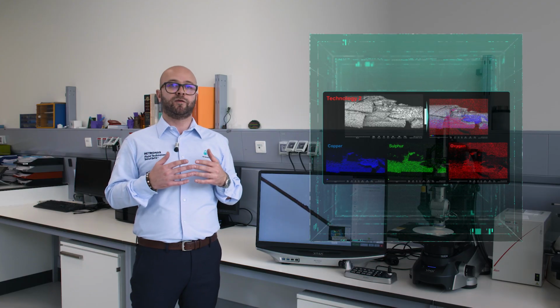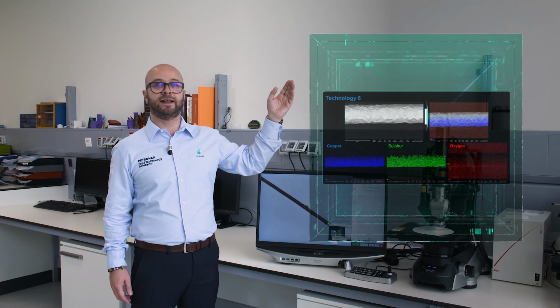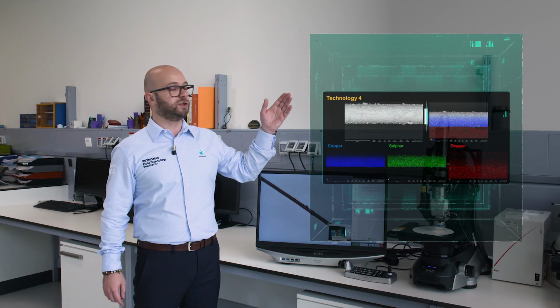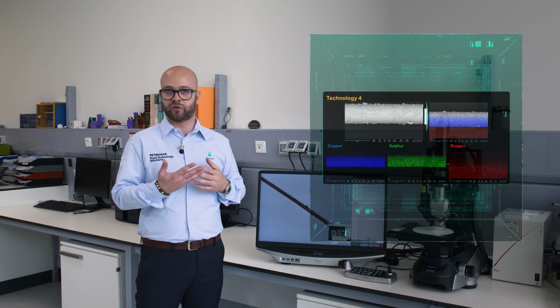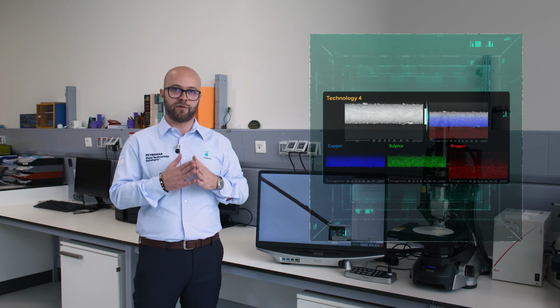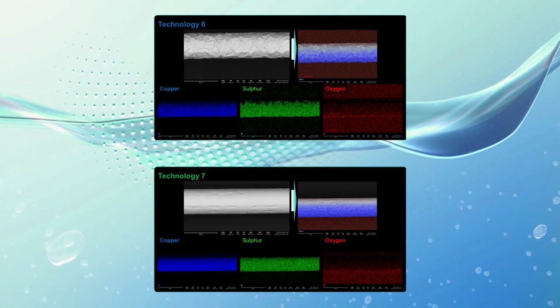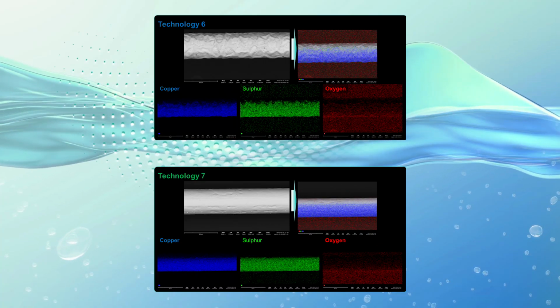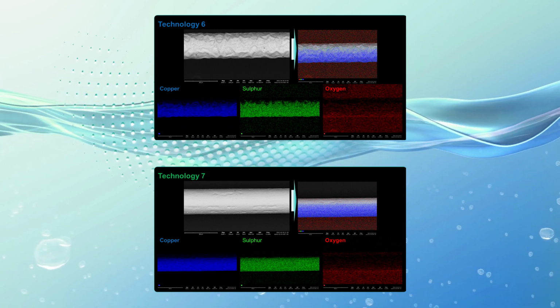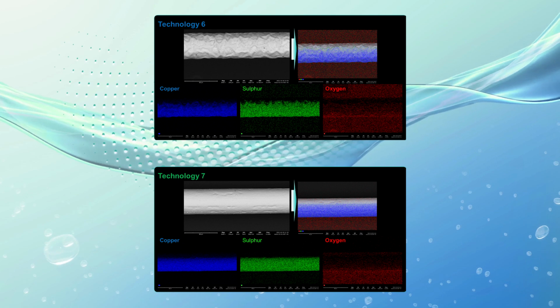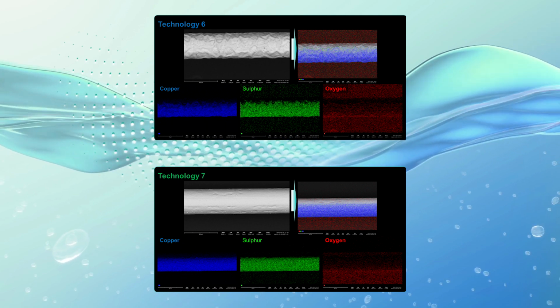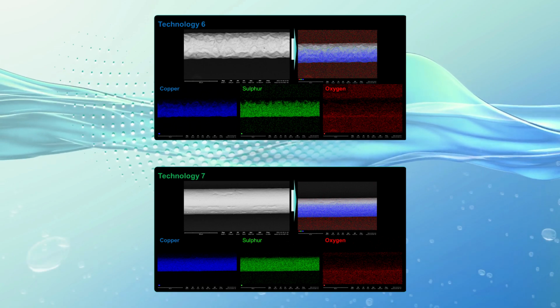Much more homogeneous and uniform is the surface for technology 4, 6 and 7. For these three technologies, we have a uniform distribution of sulfur on the surface, which clearly is due to corrosion product for technology 4, which is visible at macroscopic level together with copper, forming copper sulfide. While for technology 6 and 7, the sulfur deposited on the surface is due to the free sulfur which is present in the fluid and might interact with the surface of the wire.